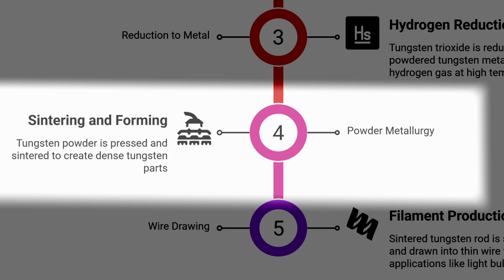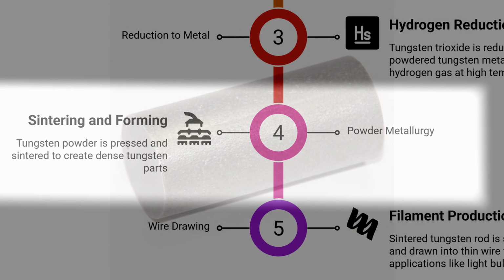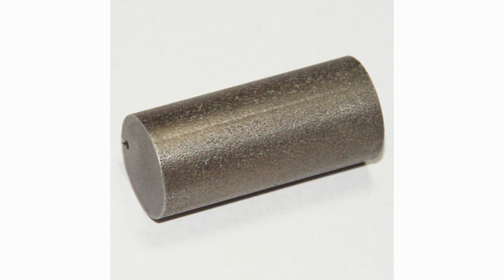The tungsten at this stage is a gray powder, not very useful as a structural material because tungsten's melting point is so absurdly high, casting molten tungsten into ingots or shapes is impractical. You need special furnaces well above 3400 degrees Celsius, which are expensive and energy intensive. Instead, industry usually resorts to powder metallurgy techniques. The tungsten powder is blended with a tiny bit of binding material, often nickel or iron powders, pressed into the desired shape and then sintered, heated below melting point, to fuse the particles together. Now, during sintering, the small additive nickel iron diffuses and helps bind tungsten grains, resulting in a solid piece. This is how dense tungsten parts like rods, blocks, or spheres are made.